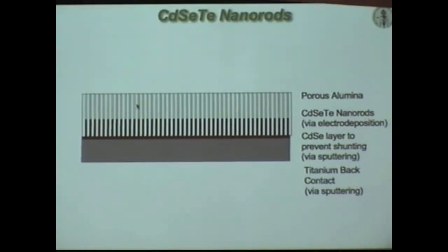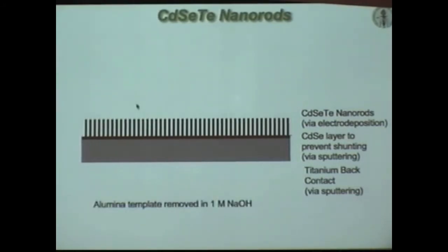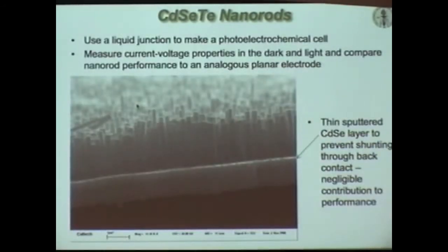The template, alumina, is soluble in base. We etch it off in base. We're left with the forest of rods that are 3 microns long, but smaller than a micron in diameter, and so we should be able to collect things sideways. And then we fill this up with a liquid that's going to collect everything that can get sideways and see what we see. Here's an example of this kind of first generation photon forest. Here's a 1 micron scale bar, long enough to absorb the light, highly dense, and there's also some photon trapping and scattering in between.